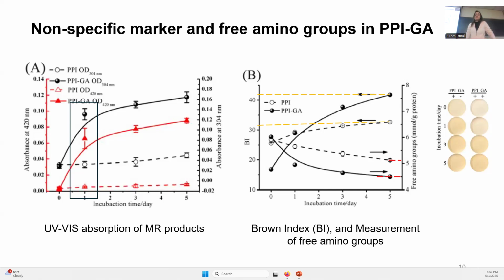And then for the free amine groups, on this side of the Y axis, we do see a high decrease. That was 18% decrease in free amine groups after the first day of incubation, while for the pea protein alone, after incubating for the same time, it was only a 4% decrease.